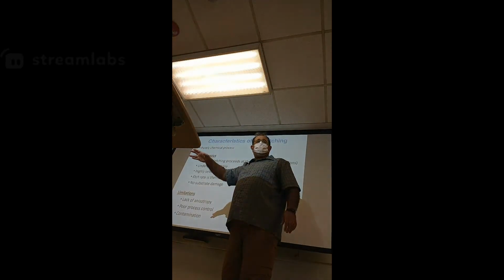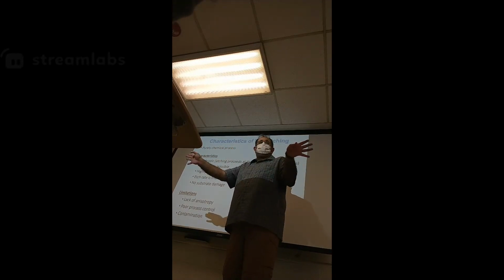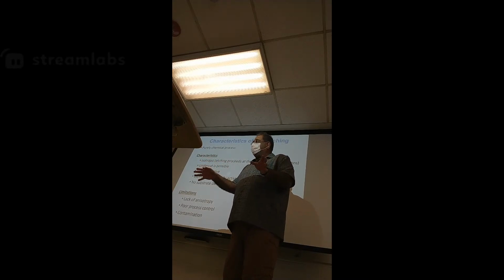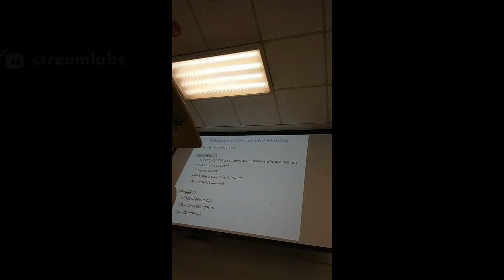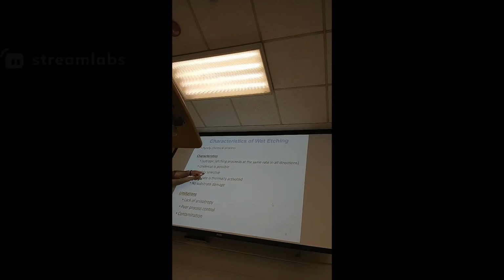That if it's isotropic, it's going to go in all directions. So you're going to have undercut. You're going to have lateral etching, okay? And we use the oxide as an example at the end of the last lecture. We talk about selectivity. What is selectivity? So if you wanted to etch silicon using oxide as a masking layer, we talk about how much of the masking layer will get consumed during the etch process for silicon, right? And that gives you a ratio. So if you have a very selective mask, you don't etch any of your masking layer, right? We use the hydrofluoric acid, as you recall, as one of the examples for the wet etching. And I say HF, hydrofluoric, etches oxide. It does not etch silicon.